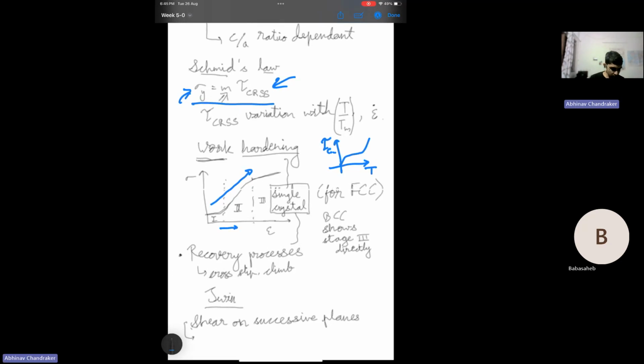In case of single crystals, what is observed is that initially there is no hardening taking place, and this region is called stage 1. After a point, there is significant hardening which occurs. The rate of hardening is quite high and it's somewhat linear. It is called stage 2. Then there is a dip in the hardening rate, which is called stage 3. This is for FCC crystals. And very briefly, I'll tell what the reasons for it are.